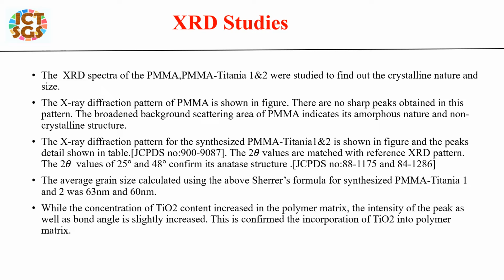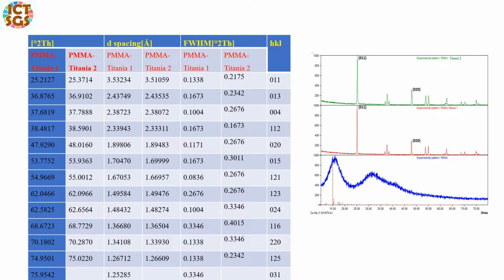The 2 theta values are matched with the reference XRD pattern. The 2 theta values of 25 degree and 48 degree confirm its anatase structure. It is also confirmed by the JCPDS file. The average grain size calculated using the above Scherrer formula for the synthesized PMMA-Titania 1 and Titania 2 was 63 nanometer and 60 nanometer. As the concentration of titanium content in the polymer matrix increased, the intensity of the peak as well as the bond angle slightly increased. This confirms the incorporation of titanium into the polymer matrix. The PMMA-Titania nanocomposite peak details are shown in the table, along with the XRD spectrum of PMMA and PMMA-Titania nanocomposites.